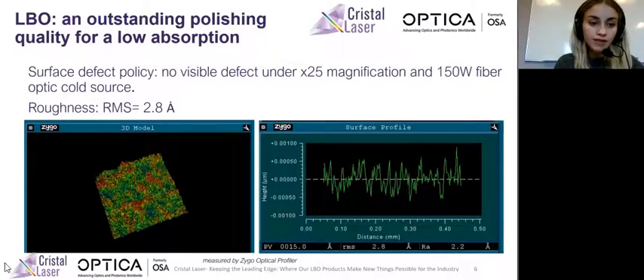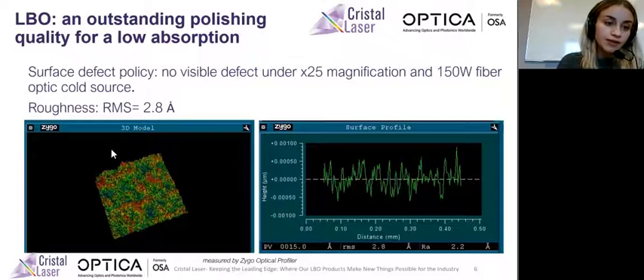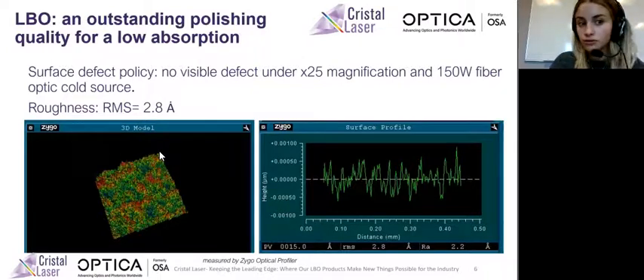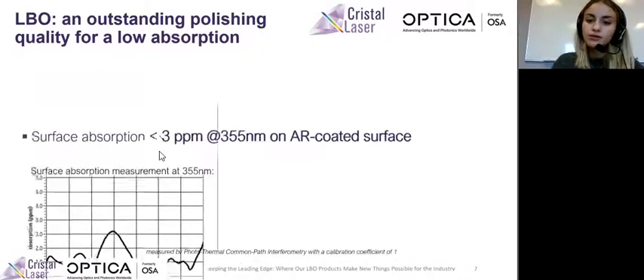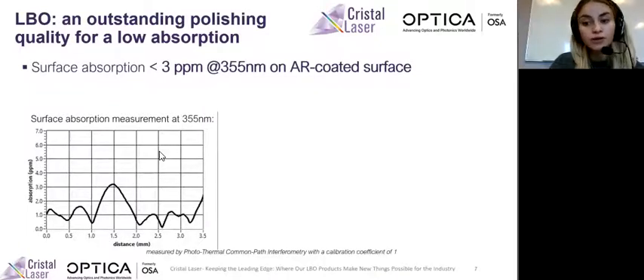You can see here on this slide the roughness measurement for an LBO crystal produced by Cristal Laser. And you can see that the roughness here is 2.8 angstrom RMS. For UV applications, we usually set the bar at 3 angstrom RMS. A roughness that low allows us to achieve an impressively low surface absorption, which is the other key parameter in enhancing the lifetime of crystals under UV.